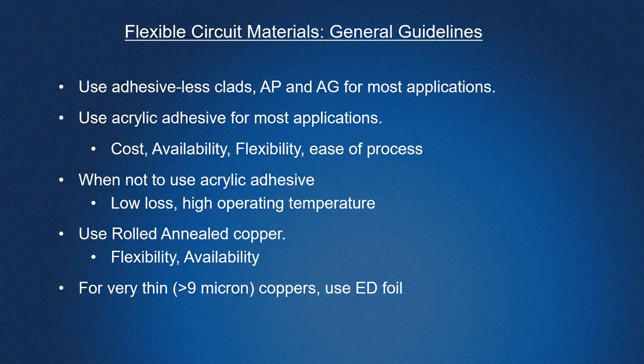Where you can run into trouble is when the material is mechanically stressed during the high temperature point where it's soft. So if the material is flexed or bent when it's, let's just say 150 or 200 degrees Celsius, it won't be decomposing, but it will be very, very soft and very vulnerable. Now, when it cools down, it goes back to normal and no harm's done. But if you have any separation or any other issues while it's at the higher temperature, you've got a problem.